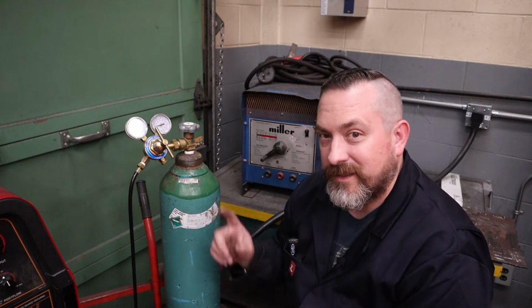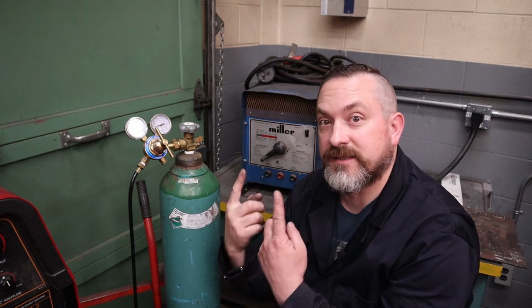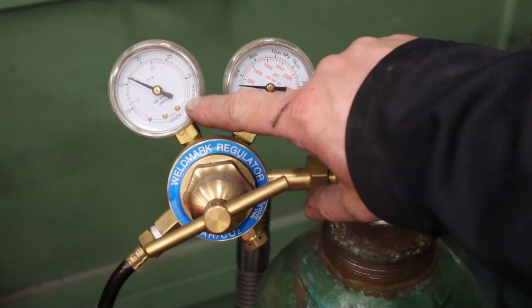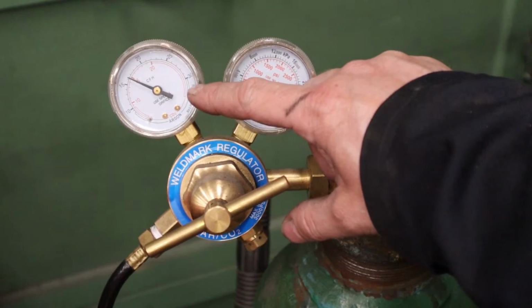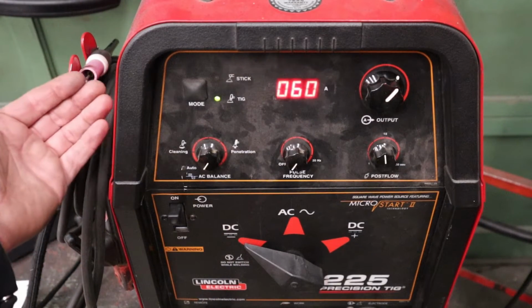Now, some general guidelines: if you do not have enough flow, then you just don't have a big enough shield of gas around your weld puddle, and you'll start to introduce some porosity from the outside atmosphere. And when you crank it up to 30, 40, 50 cubic feet per hour, that doesn't necessarily make it better. What happens is you have such fast flowing gas out the end of your electrode and out of your gas cup that it starts to cause turbulence, kind of like this, where it brings in oxygen and actually causes porosity. So you do want to get it around 15 to 20 cubic feet per hour. Now, when you go to set your flow rate, it's important that you turn on the machine and you will hear and see the flow coming out from your gas cup.